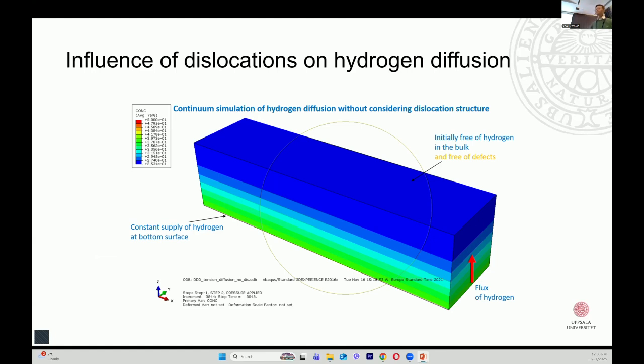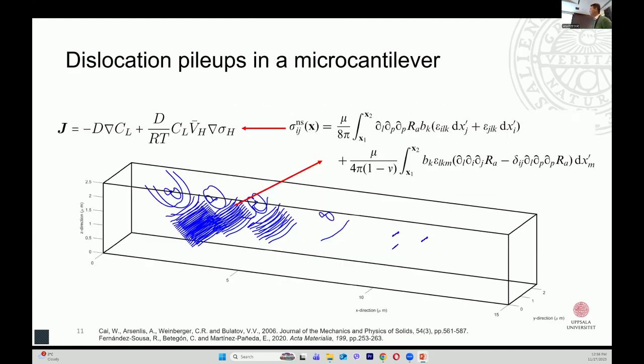And because of that, if we do not have external loading, if we do not have externally applied stress concentration, all the simulated hydrogen profiles will be uniform. So if you look at the same height, we have the same concentration. That is because the trap is smeared in the volume. But we know that in reality, we have dislocations, and dislocations are trapping sites. So could hydrogen actually distribute in a non-uniform way?